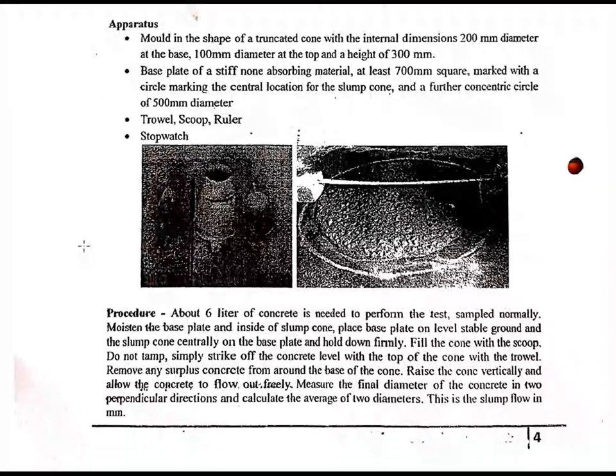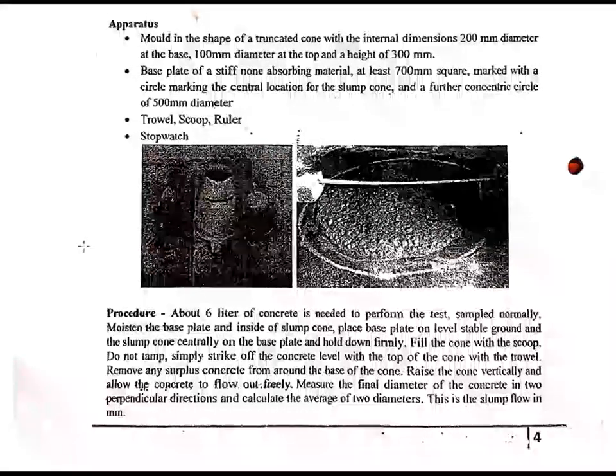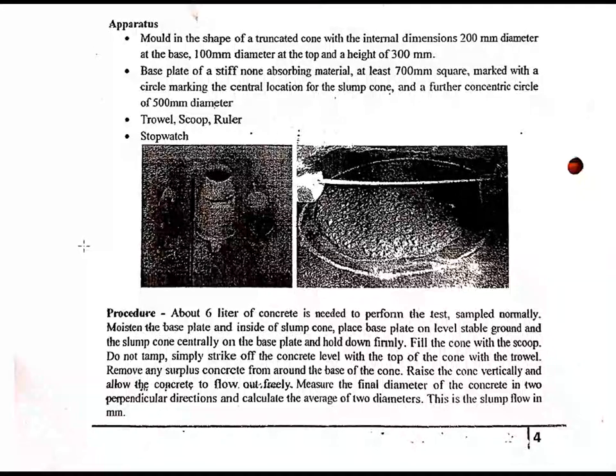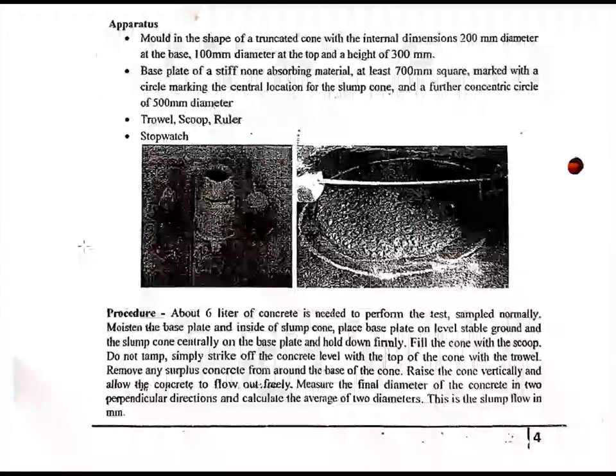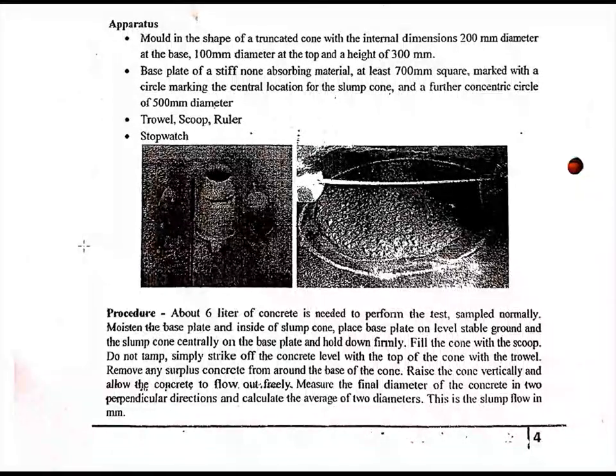To achieve around 500 mm of diameter flow, you need to note down the time. We will not know how this 500 diameter is reached, so beforehand, you need to draw a circle of diameter 500 mm. At the center of the circle, you place the slump cone and lift it so that your concrete will flow. As it flows, it reaches that ring. When it passes the ring, you have to stop the stopwatch.